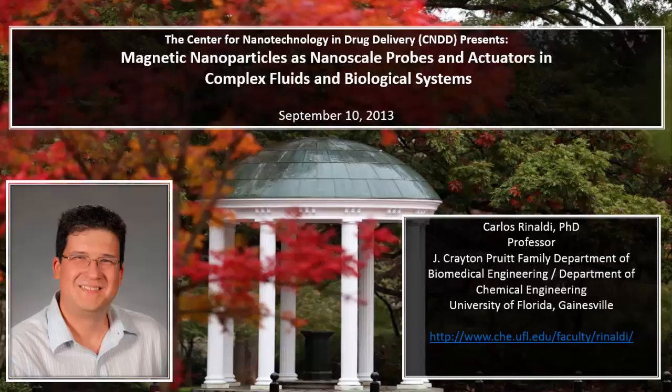So an important point that I get asked a lot, especially from Sasha in the last couple of days, is whether local heating phenomena indeed exist. And I'm not going to show you all the data that we have because some of it is unpublished. I'll be happy to discuss it offline later. But I'll show you something we have published, and that is using a thermoresponsive fluorescent polymer coating the particle as a reporter of a thermally induced change on the surface of the particle. The polymer is polyisopropyl acrylamide, and the fluorophore is such that when the polymer undergoes a transition, the intensity of fluorescence increases.